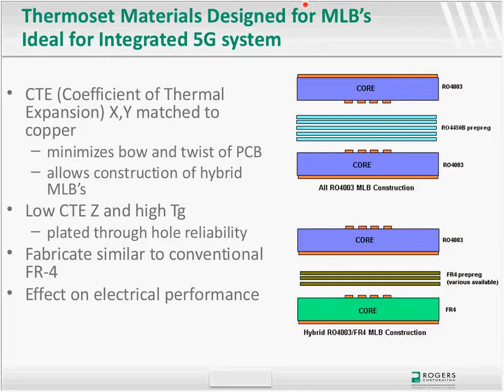The other important factor, because many of them will have plated through holes, is reliability, which is going to be very important because they may be in environments where there's significant temperature variation. So for the Z-axis expansion, pick materials with a low Z-axis expansion and a high Tg, because this will allow the via to expand and contract, similar to what we tend to see in traditional FR4 materials. When we say a low value, it's typically 80 parts per million per degree C or lower, which tend to be materials that have a high reliability. 50 is better, 40, 30. So the lower the value, the higher the reliability.